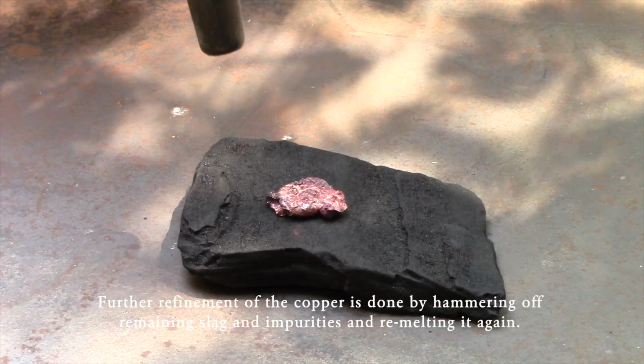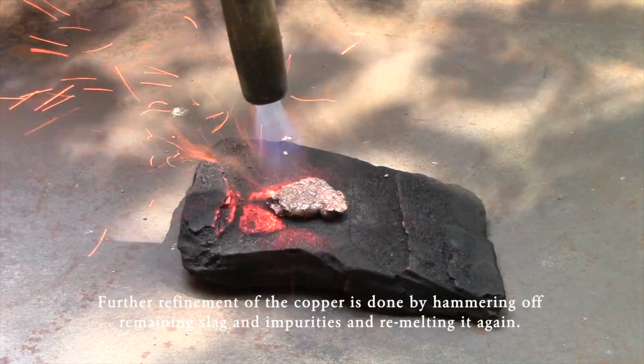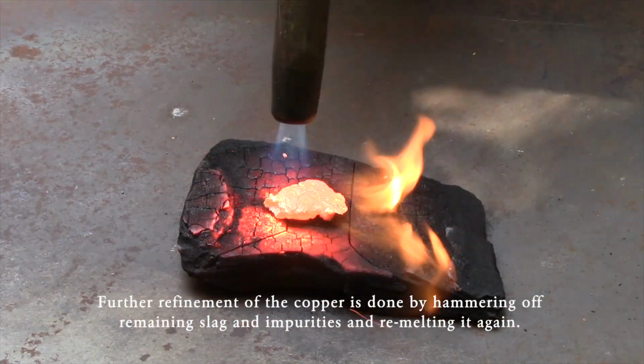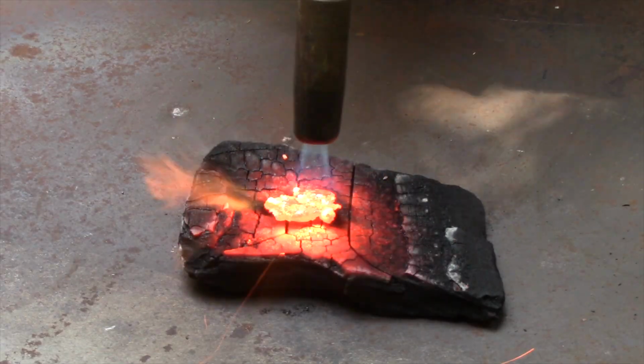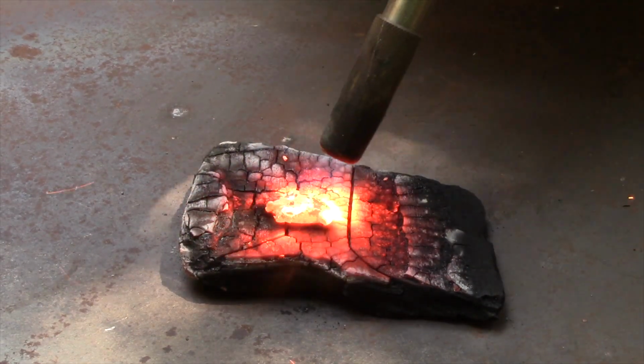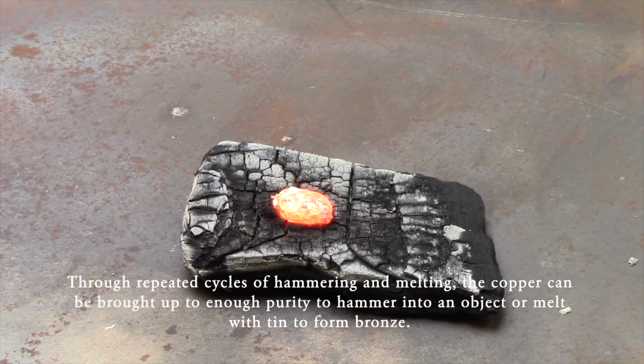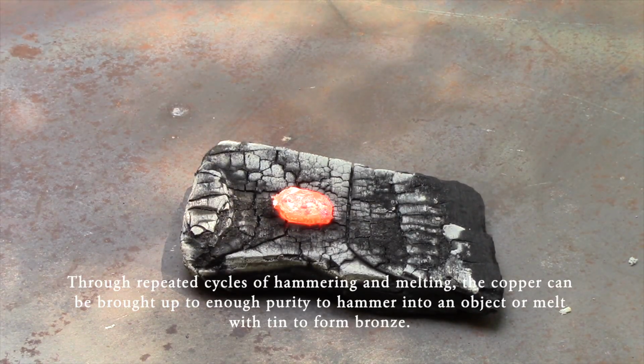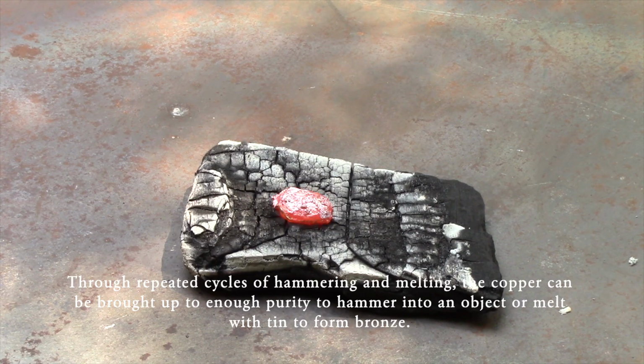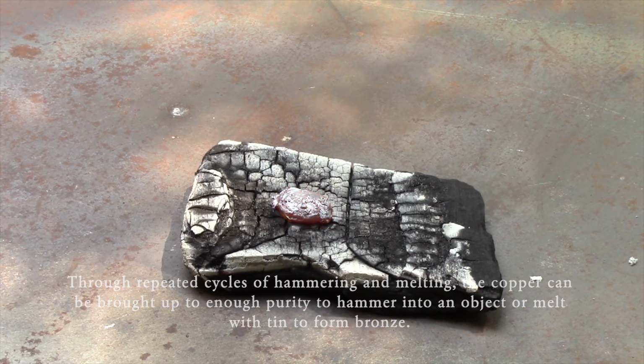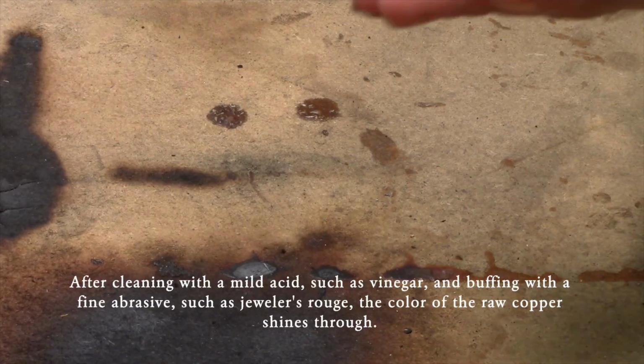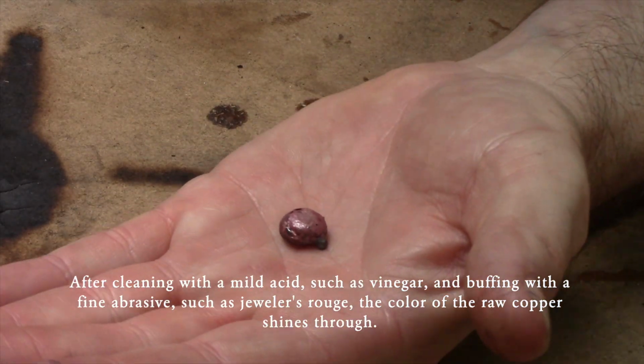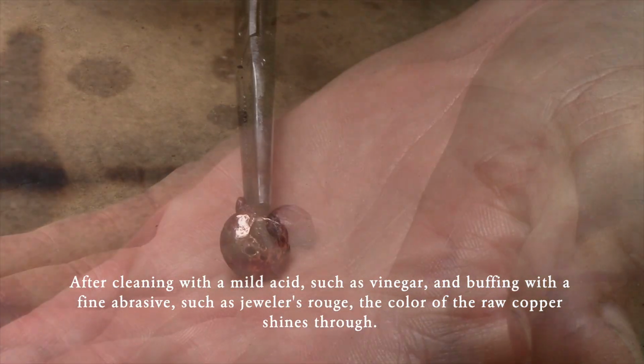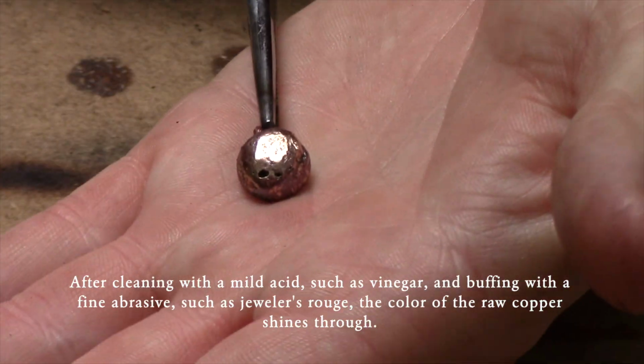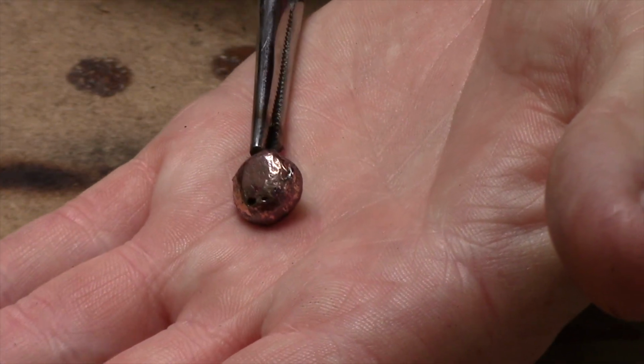Further refinement of the copper is done by hammering off remaining slag and impurities and remelting it again. Through repeated cycles of hammering and melting, the copper can be brought up to enough purity to hammer into an object or melt with tin to form bronze. After cleaning with a mild acid, such as vinegar, and buffing with a fine abrasive, such as jeweller's rouge, the color of the raw copper shines through.